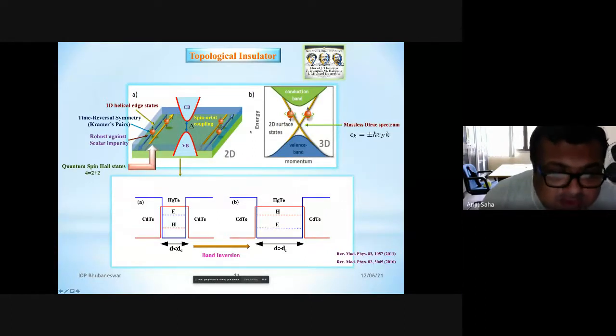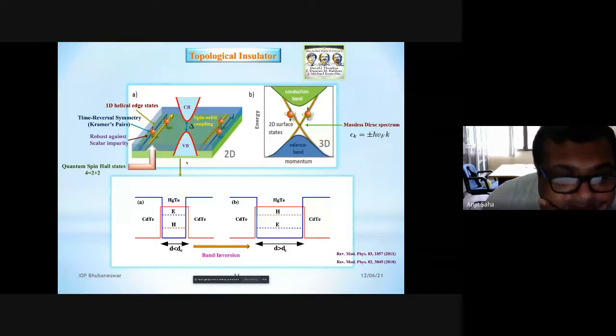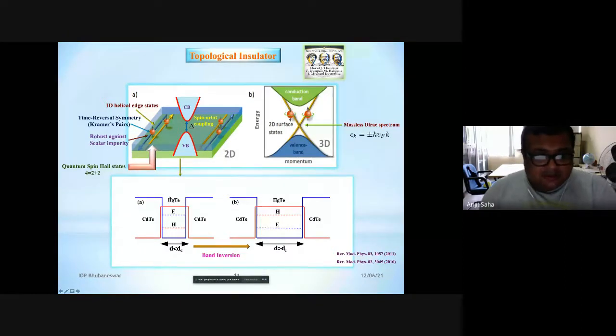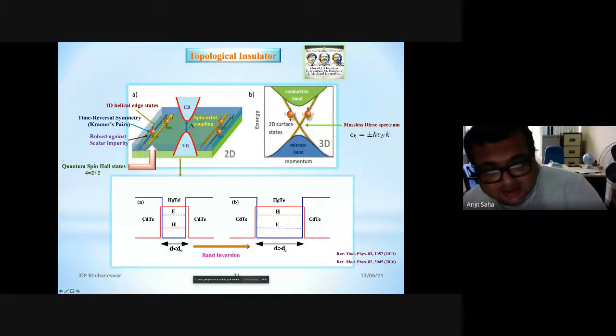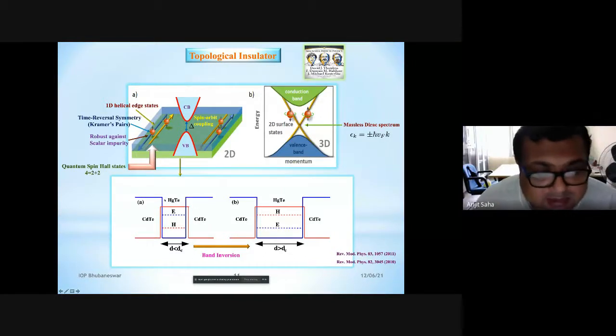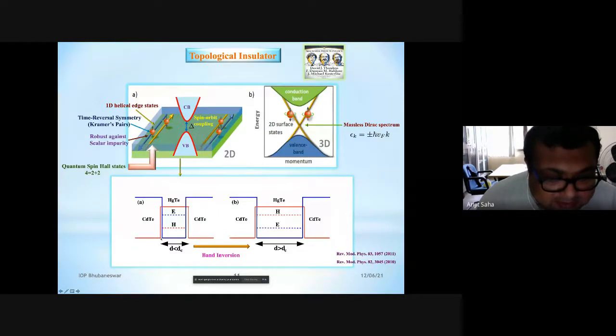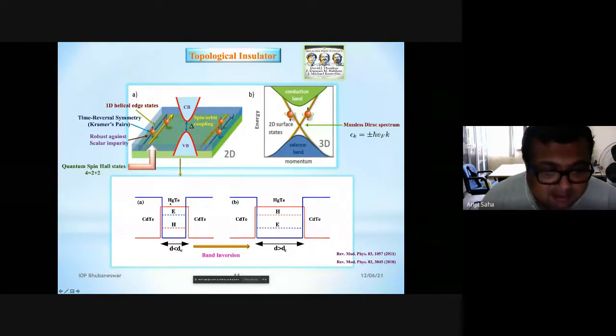So now from this 2D picture, I mean for the 2D topological insulator, let us try to understand what is the necessary mechanism to have this feature. From the practical point of view, this 2D topological insulator was first proposed in graphene, but as we know, pristine graphene has very small spin orbit coupling. So that theoretical proposal was not possible to verify in experiment. But it has been verified in another material, mercury telluride.